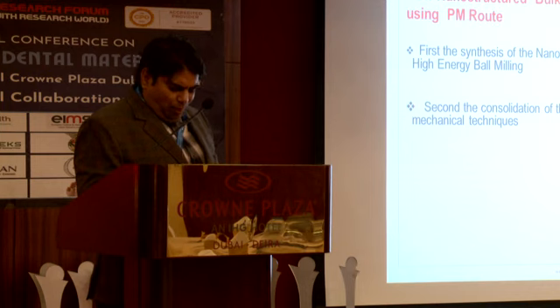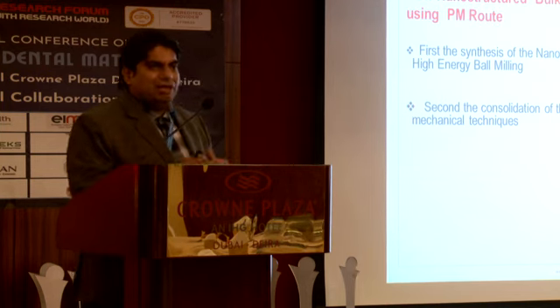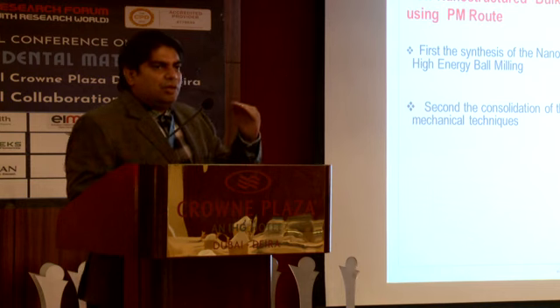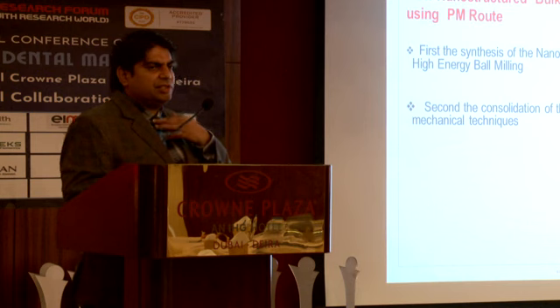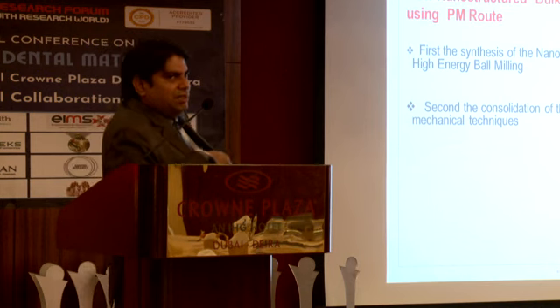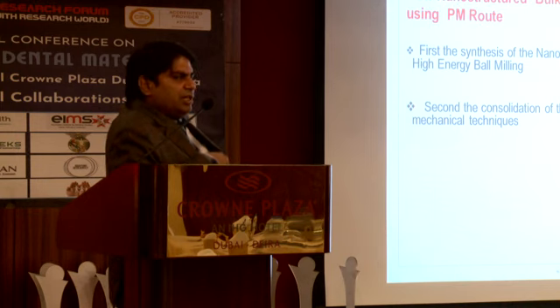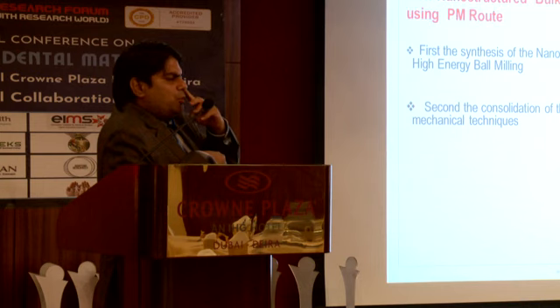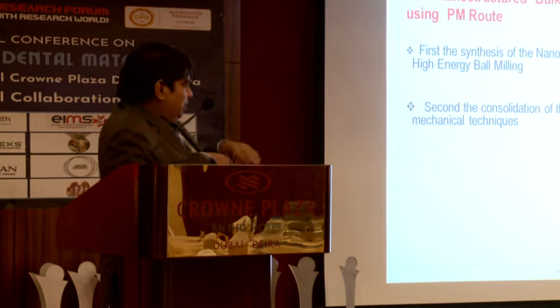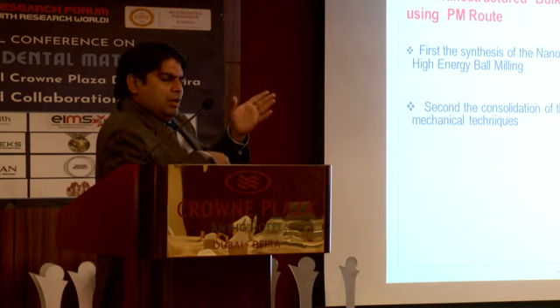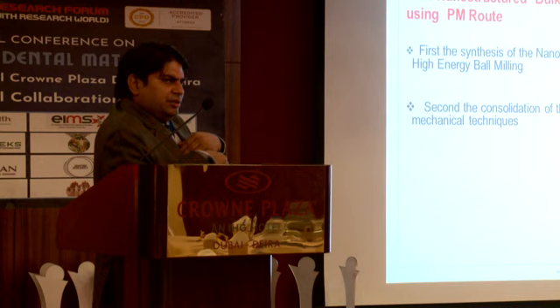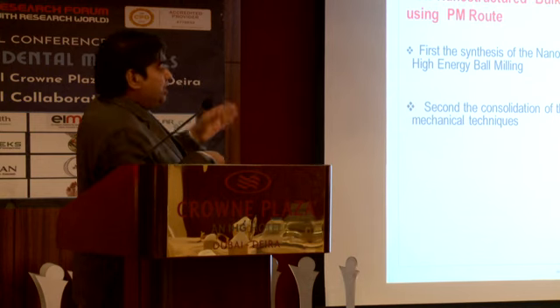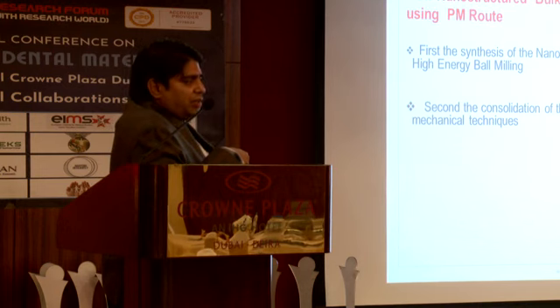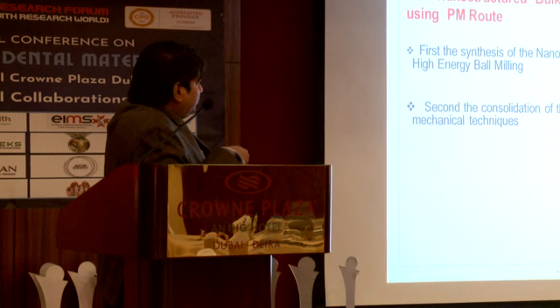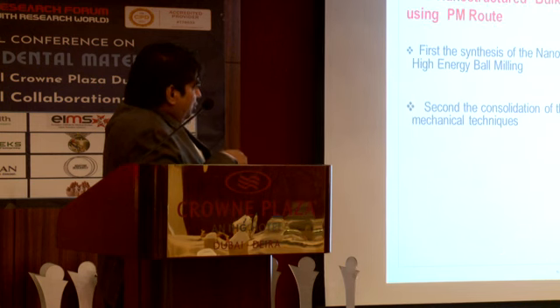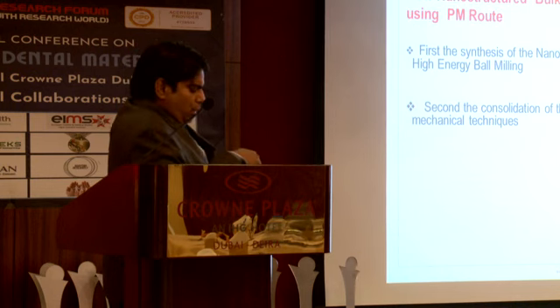So producing these powders reduces the processing temperature to much lower temperature. For example, in some cases 900 degrees centigrade with respect to the coarse-grained counterparts. And in the case of nano and submicrocrystalline grain size materials, the material can be processed at 700 degrees centigrade. It reduces the brittle to ductile transition temperature. Because of that, the processing will be amenable. That is why it is beneficial to produce these powders, and further they can be consolidated so that the grain sizes will be in control. Later on that is the consolidation of these powders by thermomechanical techniques. That is what you do.